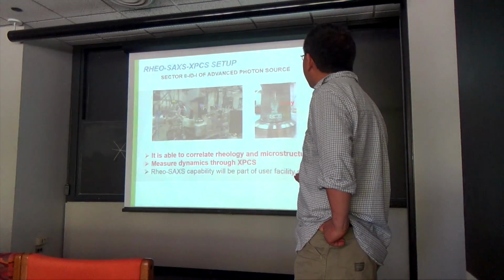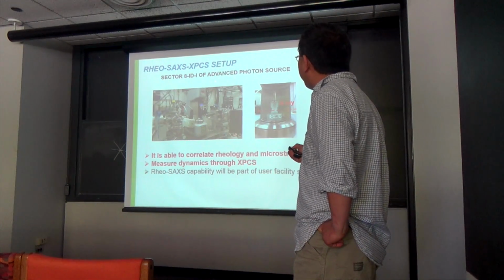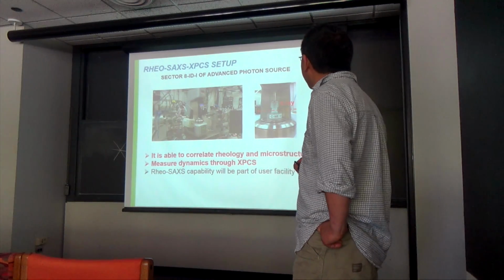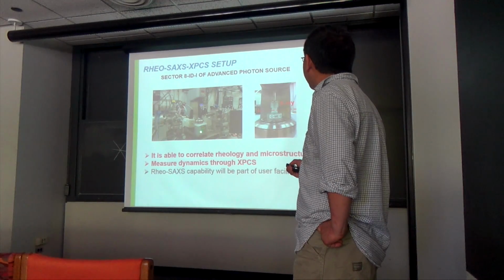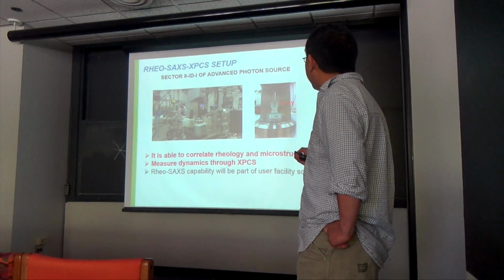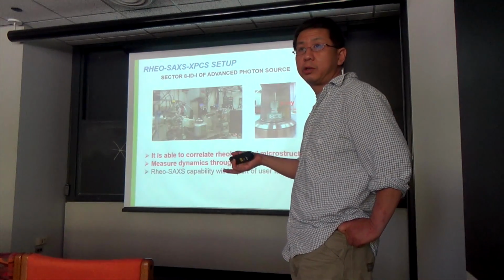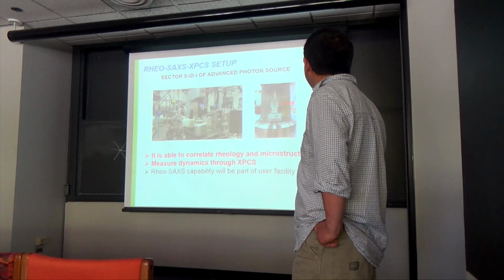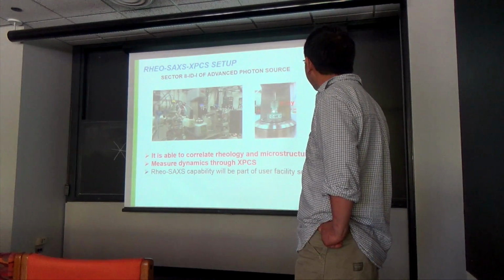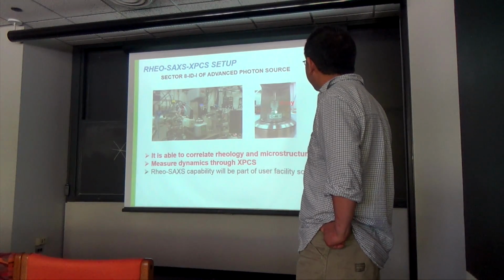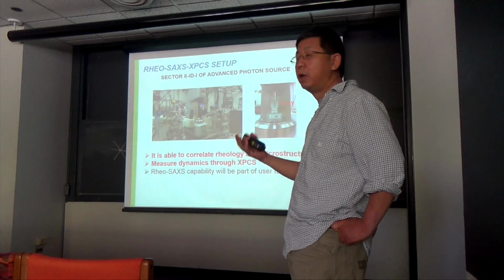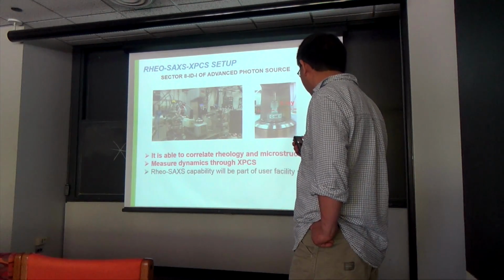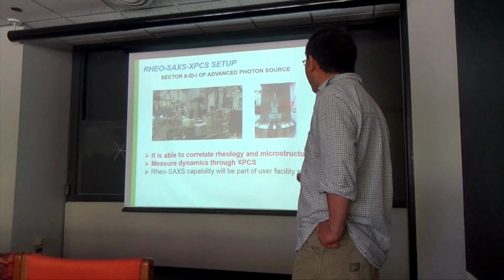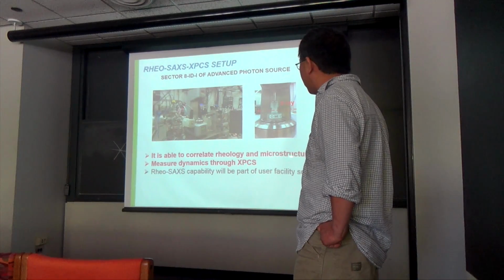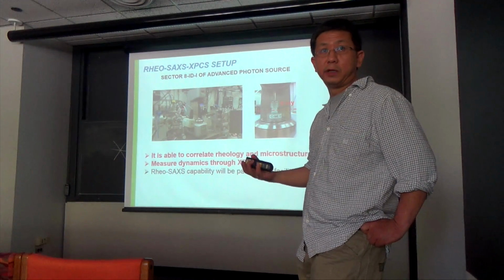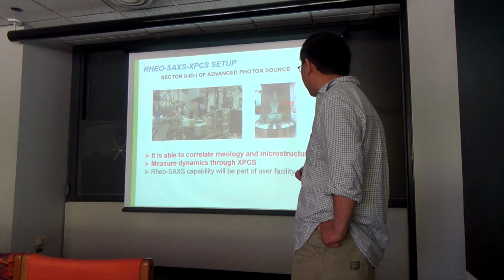Another thing is the Rheo-SAXS XPCS setup that I taught you about. What we do is we put Anton Paar rheometers on the X-ray beamline, sector 8. This X-ray beamline is specifically engineered to do SAXS and XPCS. The X-ray comes in and goes through these polycarbonate shear cells. We have a cuvette shear cell. And of course, we are hoping to gradually develop different geometries of shear cells to look at the X-ray from different directions. So it is possible to use this setup to look at rheology and the microstructures, right? And also measure the dynamics of the particles' motions through photon correlation spectroscopy.